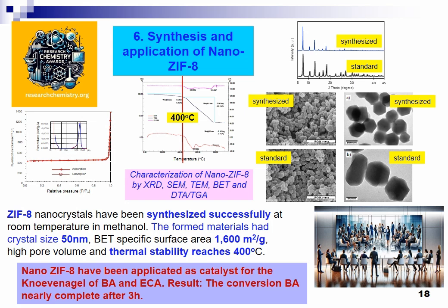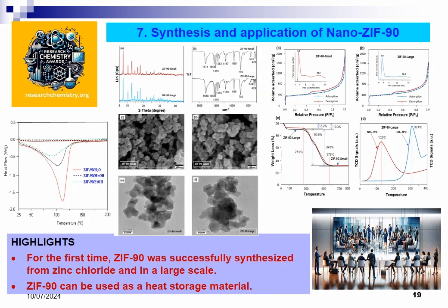6. Synthesis and applications of nano ZIF-8. ZIF-8 nanocrystals have been synthesized successfully at room temperature in methanol. The formed materials have a crystal size of 50 nanometers, high specific area, high pore volume, and thermal stability reaching 400 degrees centigrade.